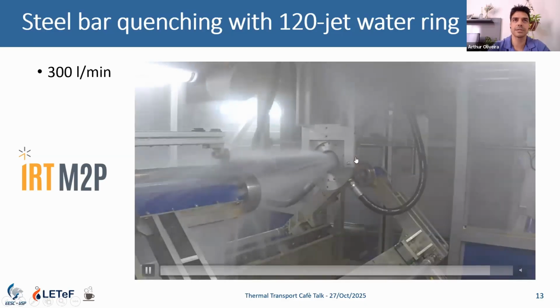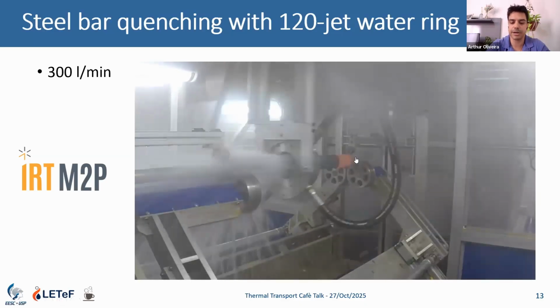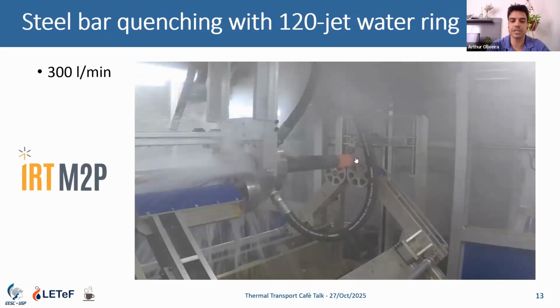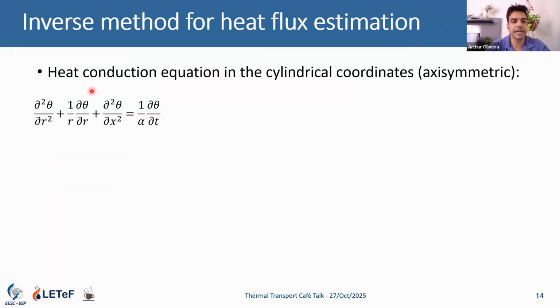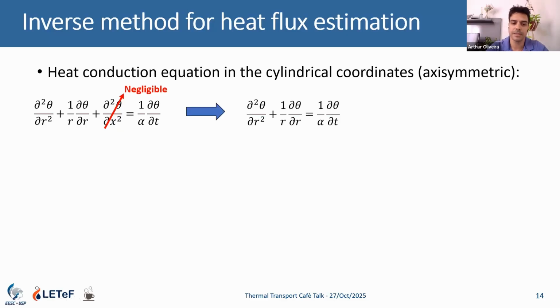To quantify the results, it's not only the temperature measurements that matter. We want to quantify the dissipated heat, the heat flux as a boundary condition for this bar. We consider constant properties, an axisymmetric problem for cylindrical coordinates. After a few simulations, we realized we could neglect the axial heat transfer, the heat conduction in this process, to quantify the heat flux.